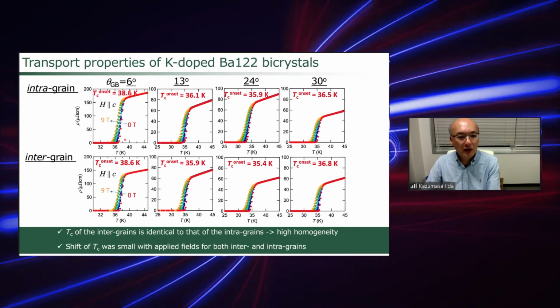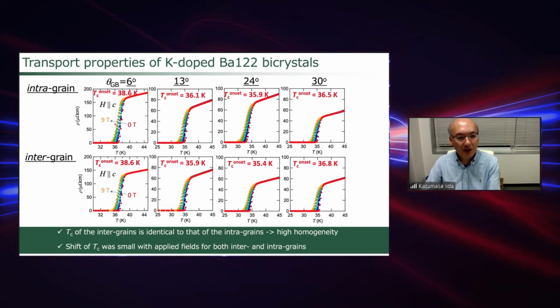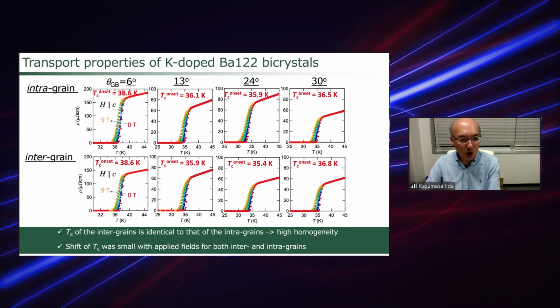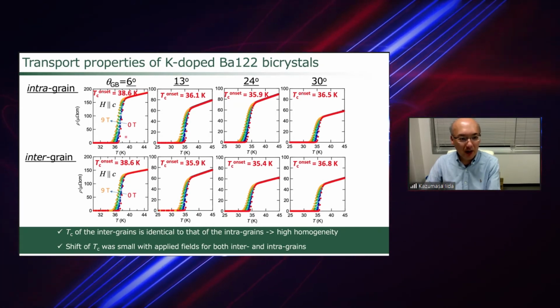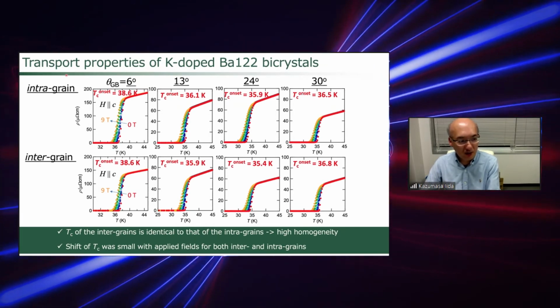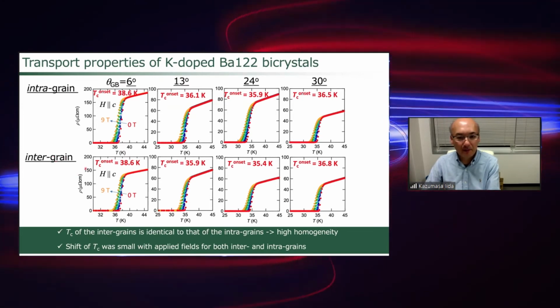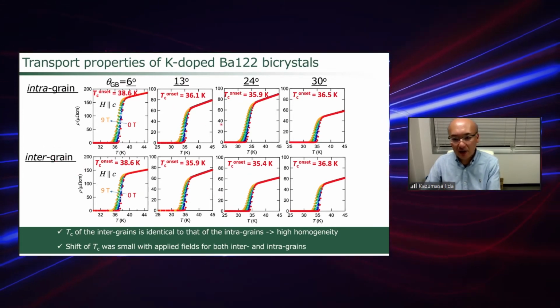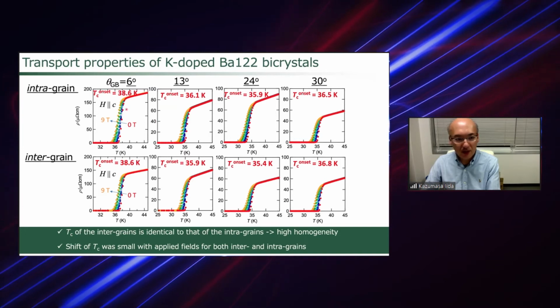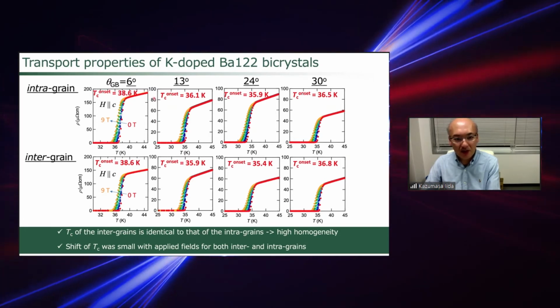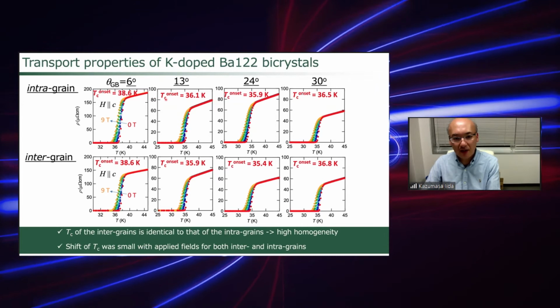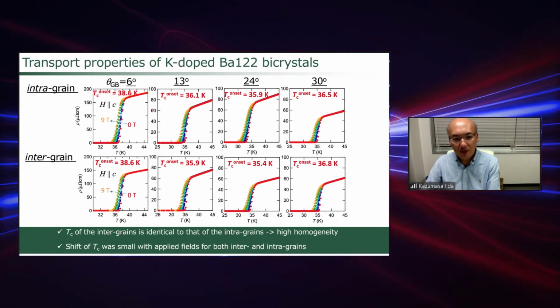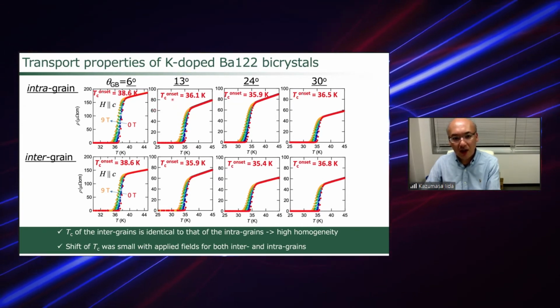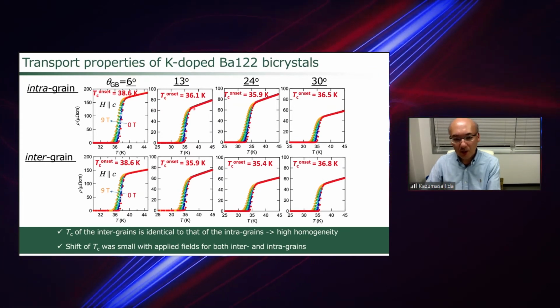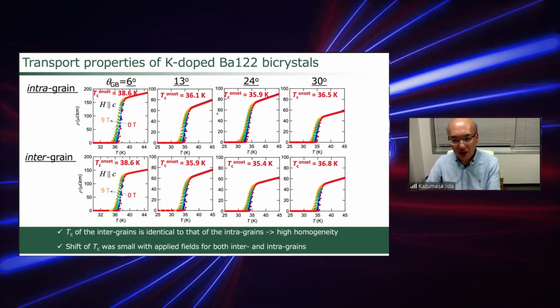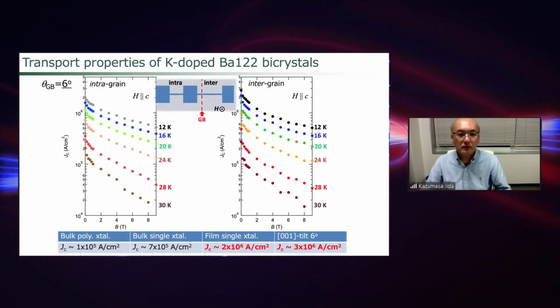And also, when we apply the magnetic field, the shift of the Tc is quite small, and it is almost the same for intragrain as well as intergrain. The other grain boundary angles are also the same as the 6 degree, but the Tc is slightly lower compared to this one, because we intentionally made the films overdoped for these three angles.